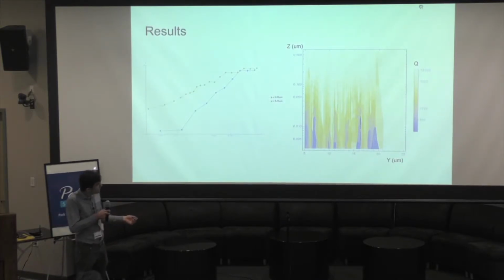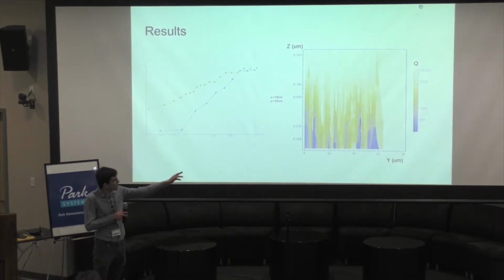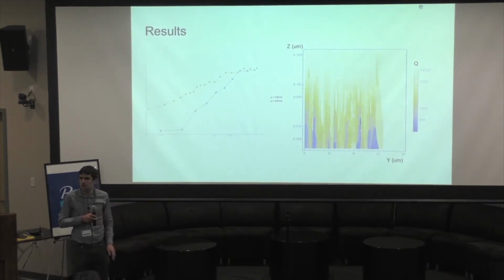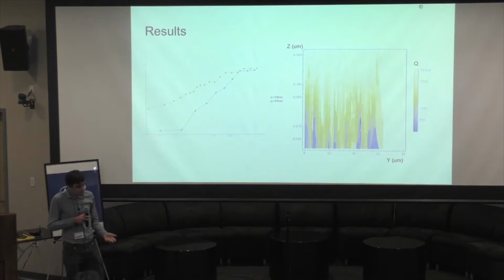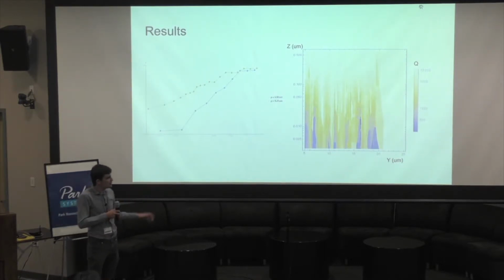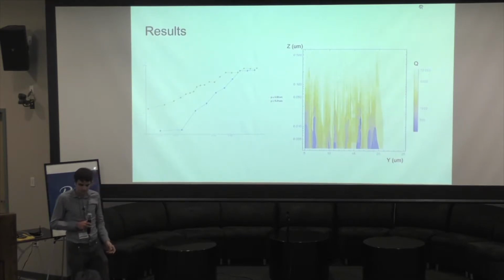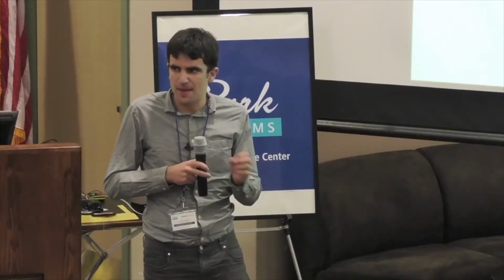But what's interesting is that in the scanning measurement, you do see some kind of periodic structure with lattice spacing on the same order as the patterning of the suspended graphene holes. So that shows promise for future work and better characterization of the sample.